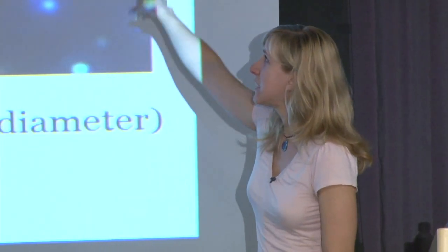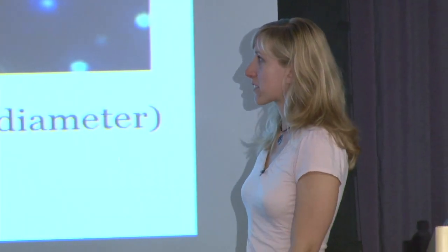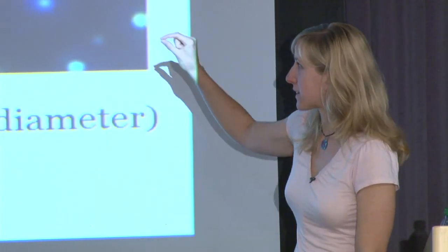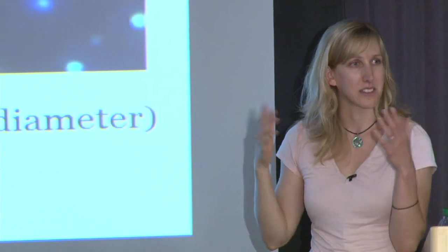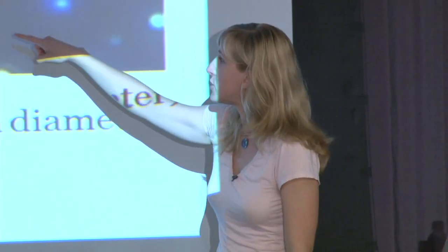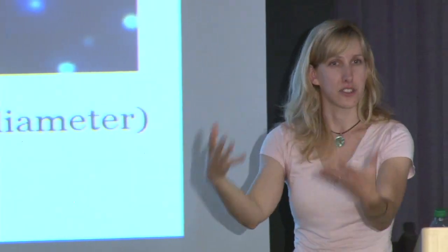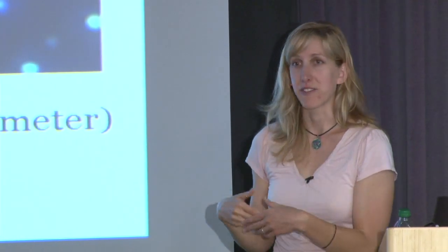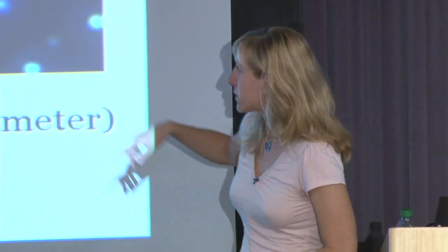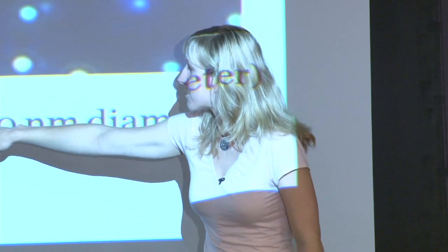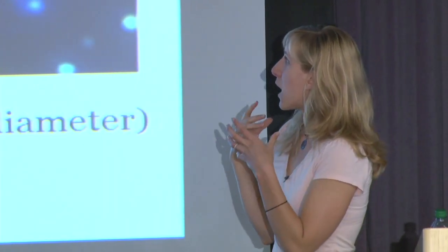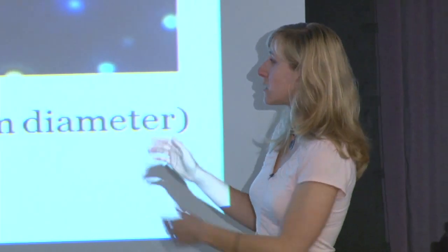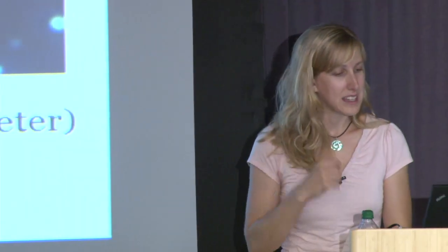And note that here, we're just looking at an optical micrograph. So what we're seeing is basically a diffraction-limited spot. So for the nerds in the audience, you're not imaging the actual size of the nanoparticle. You're just imaging the light emanating from the nanoparticle. So the size here doesn't really relate to the size of the nanoparticle. It's the color. So small nanoparticles look more blue. Larger nanoparticles look more red when they're metallic.